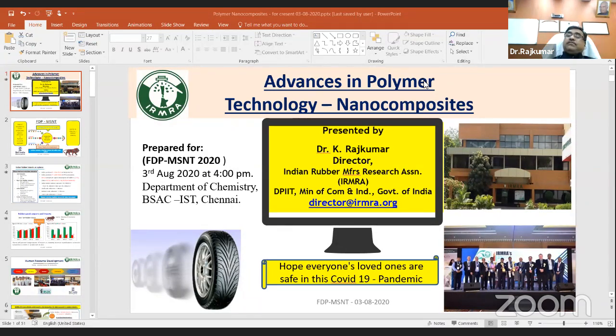He's asking, what happens when silicone polymer composites with CNT in different ratio? Yes, with the dose, the mechanical strength improves, and the tear resistance improves, because silicone rubber as such has very weak mechanical strength. It has high temperature resistance and low temperature resistance compared to other rubbers. But when we add CNTs, it can even increase the temperature resistance, and mechanical strength will be more, which is normally comparatively lower than other rubbers. So the strength will improve, and heat resistance will further improve. These are the advantages one can get out of that.